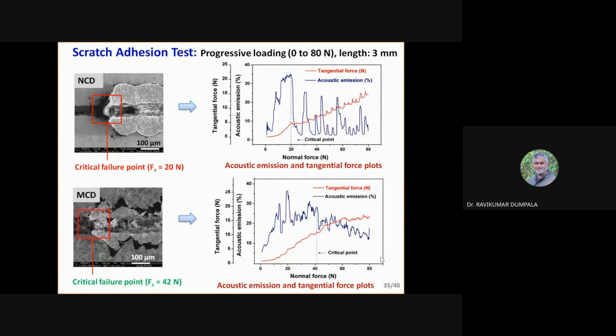The top one is nanocrystalline diamond and below is microcrystalline diamond. From the right side figures, I don't need to explain these much, it is a scratch test. When the nib comes in contact with the substrate surface, it behaves differently. It emits a different acoustic signal, or different friction characteristics. Automatically, you'll be able to distinguish where the coating has failed. From the outcome of this picture, the microcrystalline diamond is showing better scratch resistance. It is sticking hard to the surface. The nanocrystalline diamond has poor adhesion resistance, meaning it is not sticking properly to the surface.